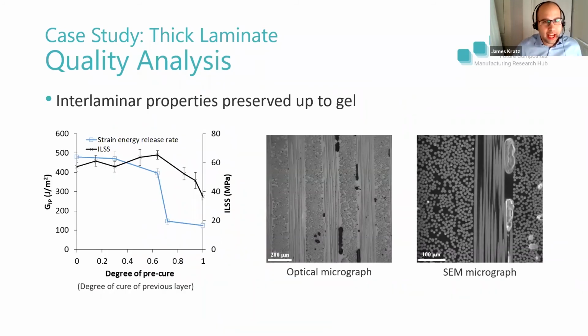And through testing of what happens in the interfaces, what we were able to identify was that if we are able to keep the degree of precure of the sublaminate to gelation or a little bit lower than gelation, we can preserve the interlaminar properties measured by double cantilever beam testing in blue or interlaminar shear testing in black.